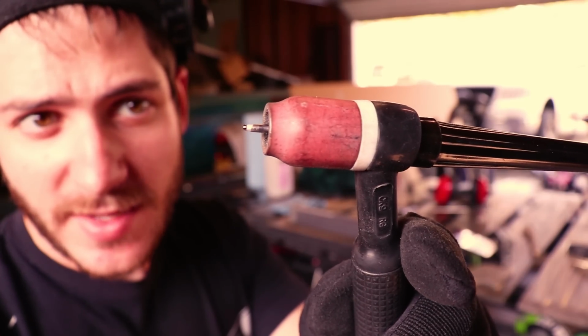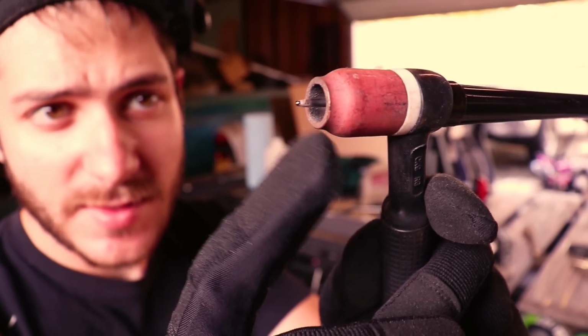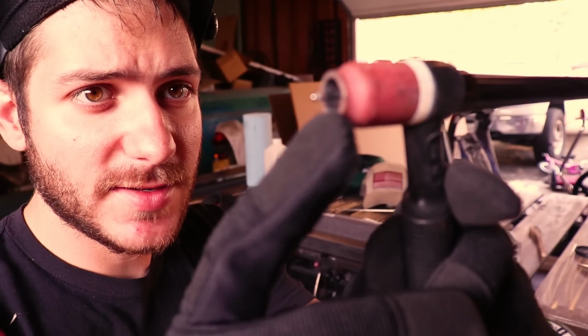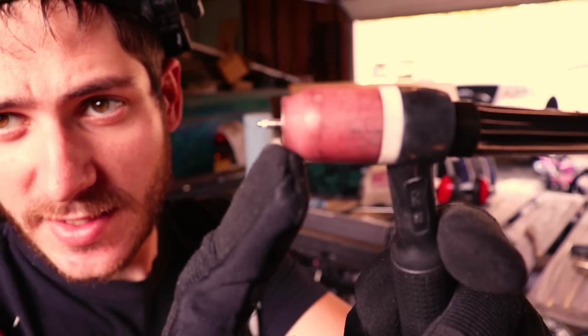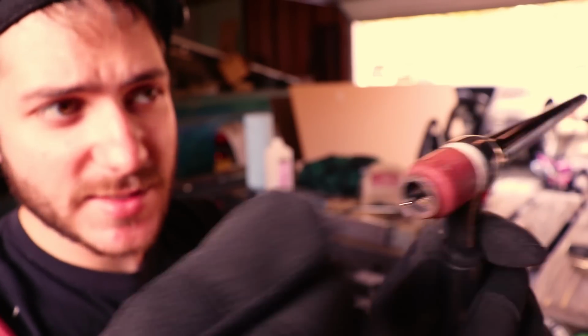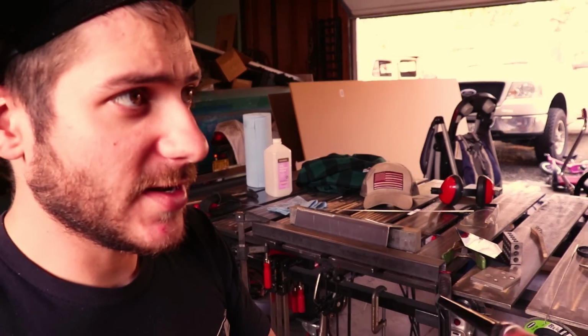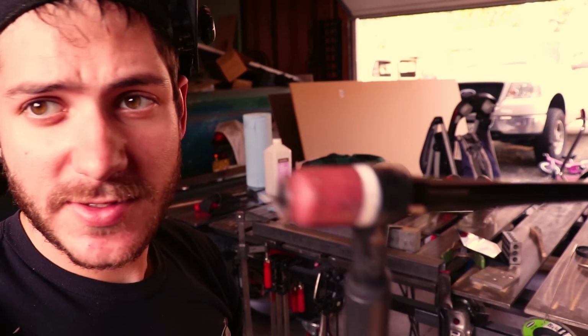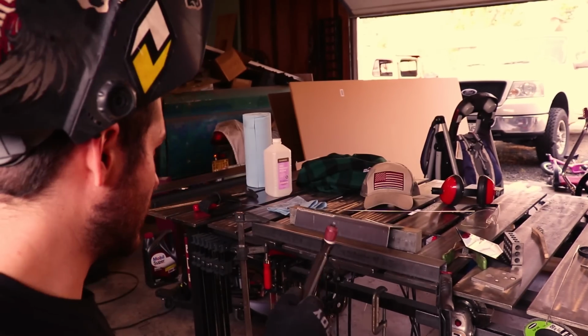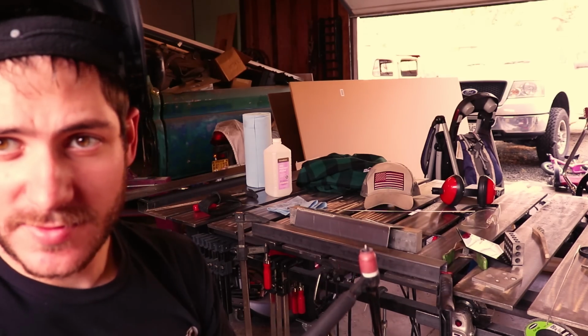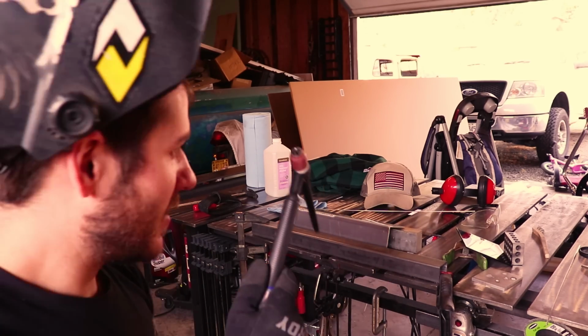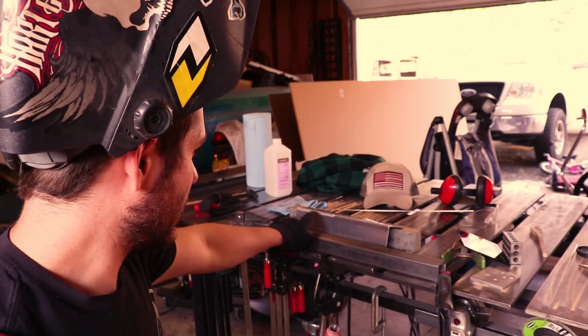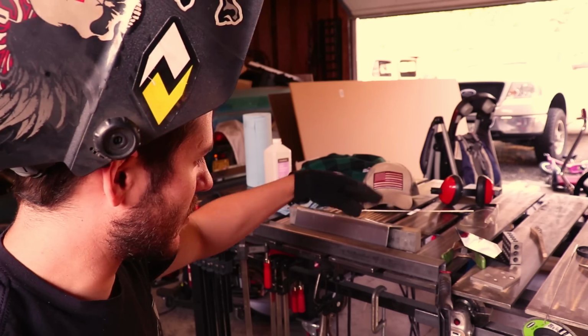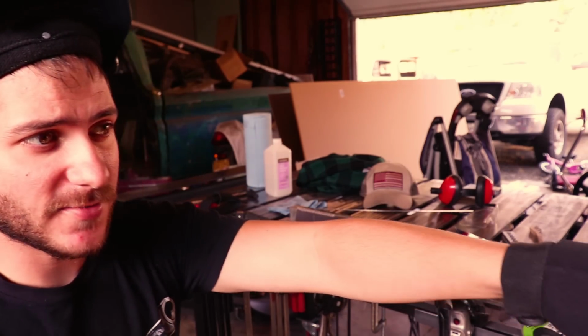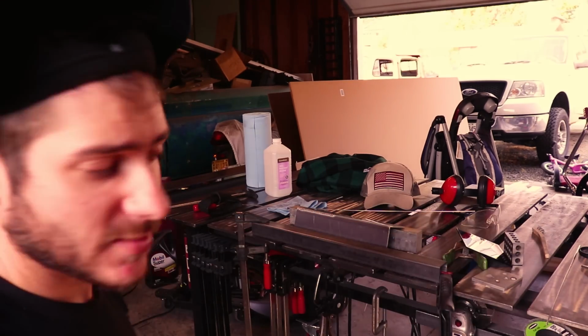Now that's the setup I have right now. I have probably, I don't know, maybe 3/8 of an inch stick out on a number 7 gas lens, and I'm running 15 CFH. I don't run very much gas on aluminum. If you start running 20 and above, it starts graying out your weld and it looks super frosty, and also your arc will start dancing, especially if you're only running like 60 Hertz.